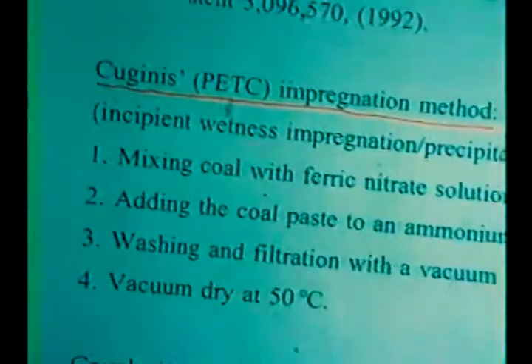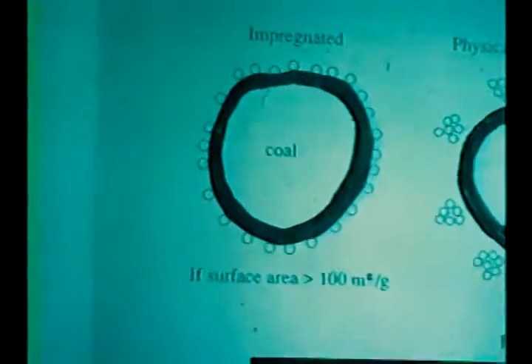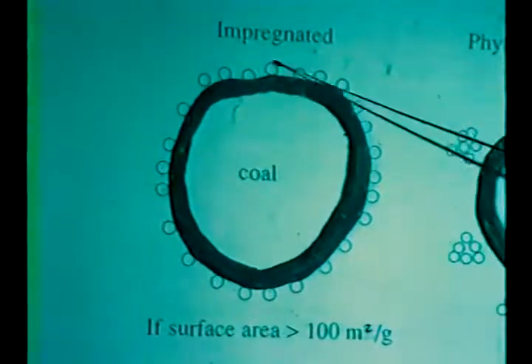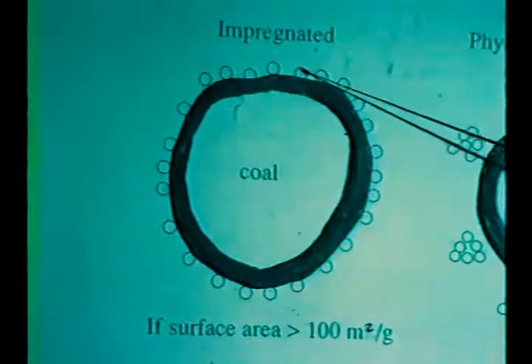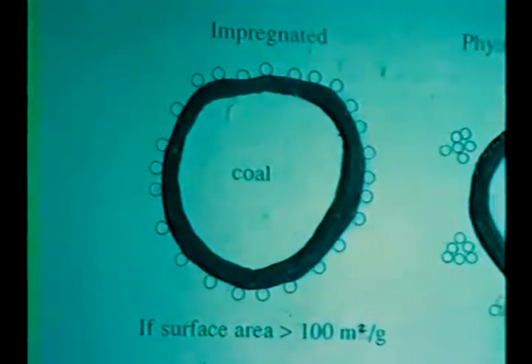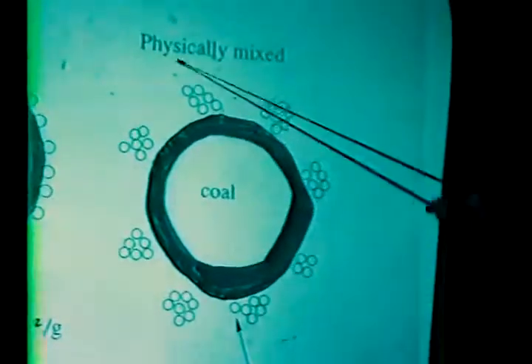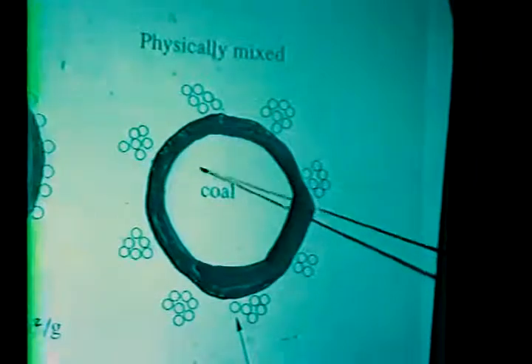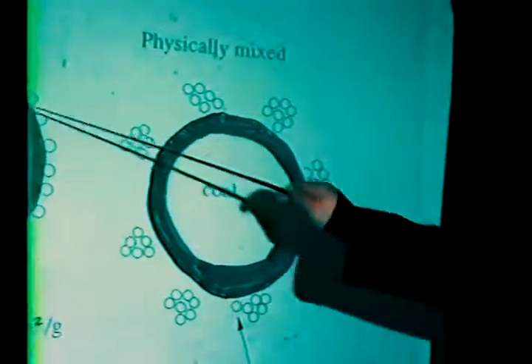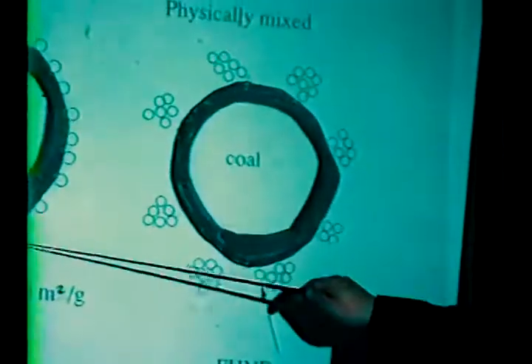The full name of the method is called the incipient wetness impregnation precipitation method. This is a method people use for supported catalysts. So what he says is the following: if you use this method, you will have ferrihydrite impregnated at the surface of the coal. If you simply mix the ferrihydrite catalyst with coal, then you have less contact between the catalyst and the coal. So you might think this is better.